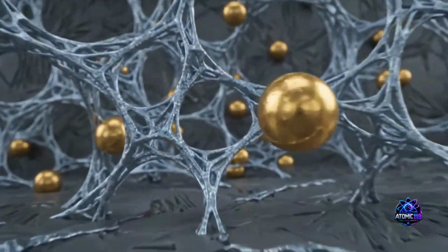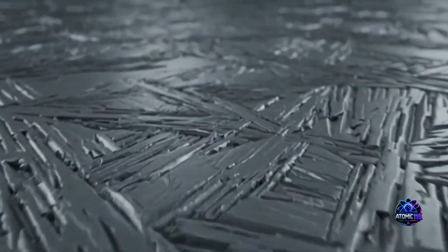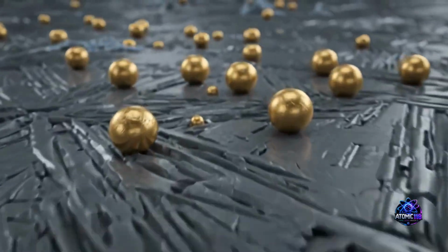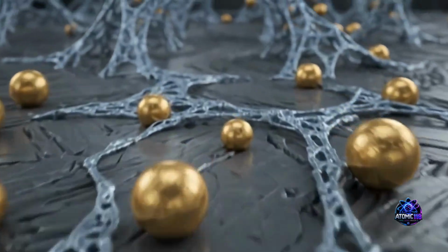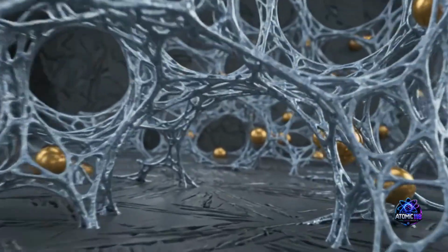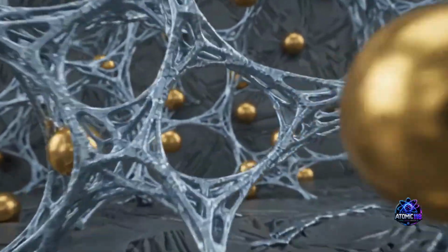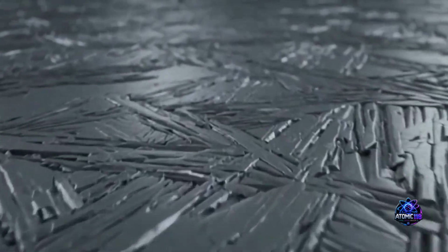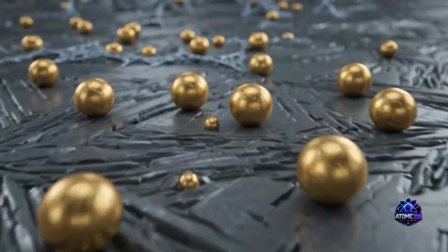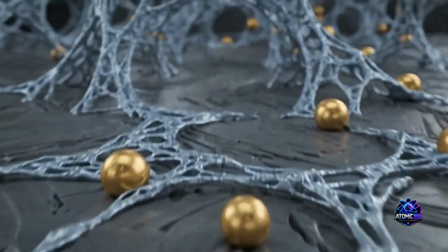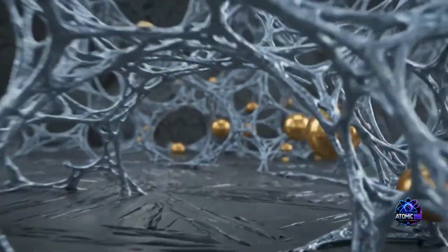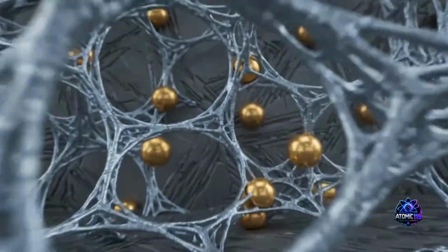But cementite is brittle. Right? Very brittle. It's almost ceramic in its hardness. Right. But when we introduce molybdenum and vanadium into that liquid mix, they don't just passively float around, they actively hijack the carbon to form their own specialized carbides. Oh, they absolutely dominate the carbon chemistry of the alloy. And they do it in completely different ways, dictated entirely by those atomic profiles we just discussed.